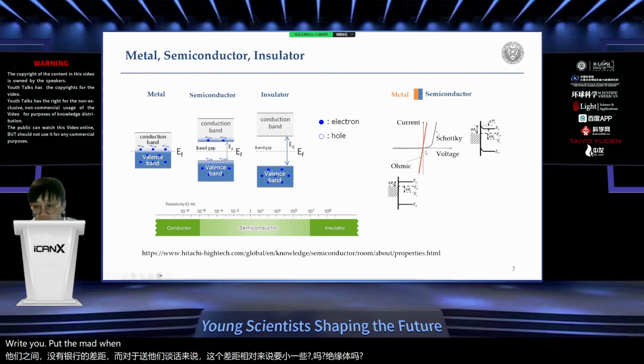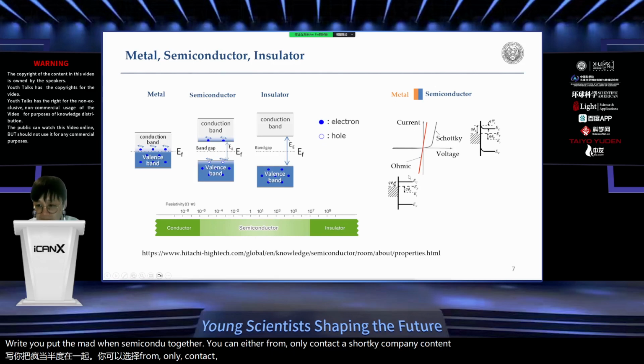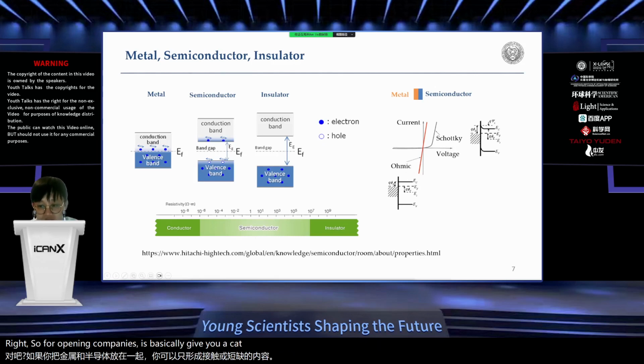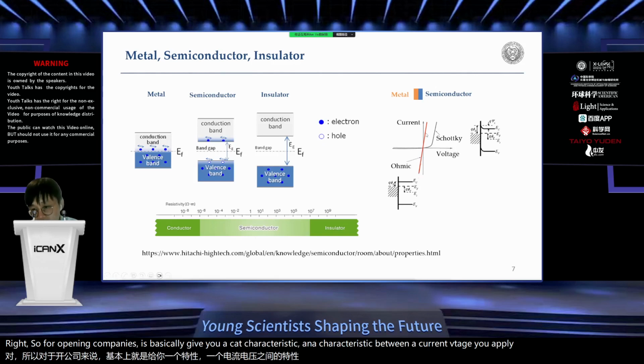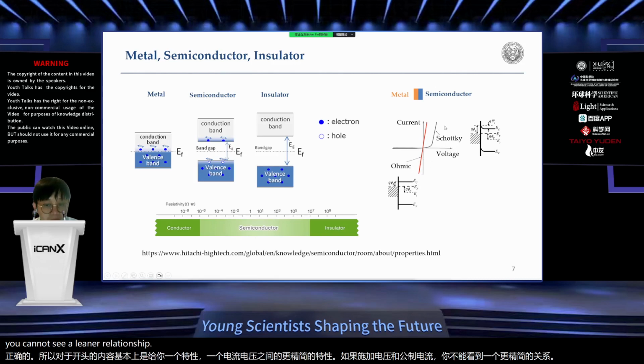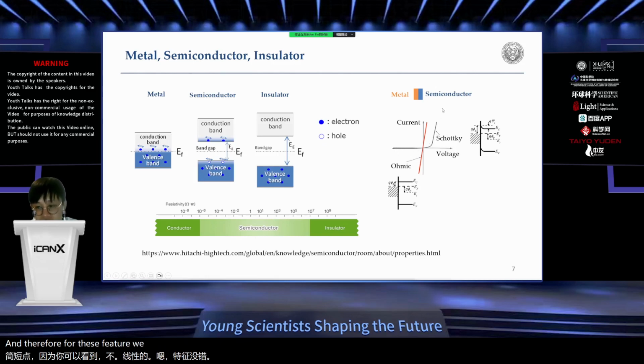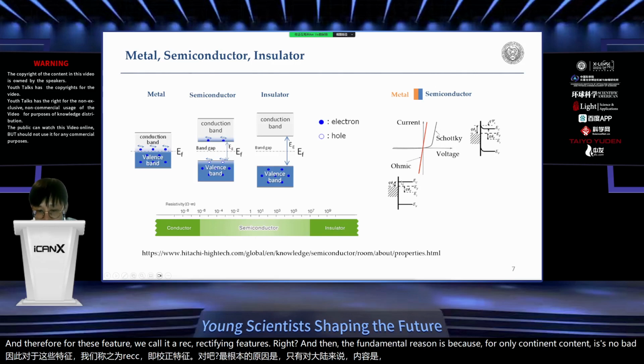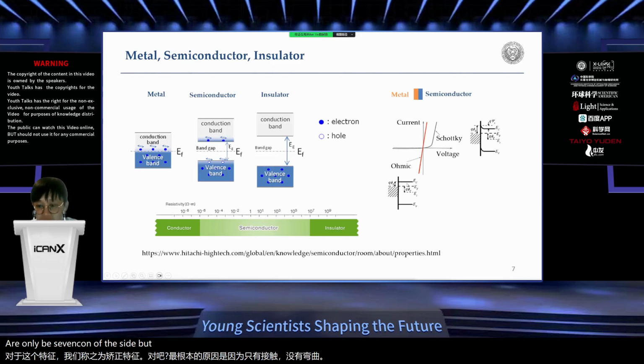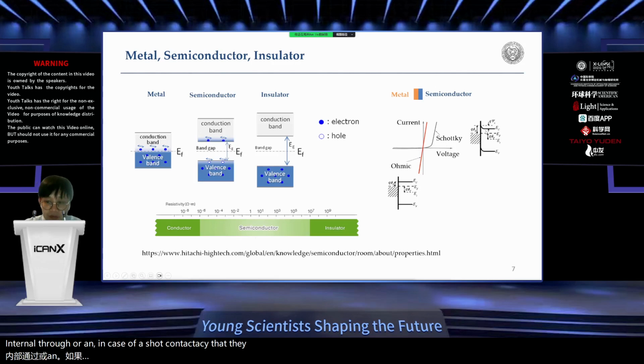And if you put the metal and semiconductor together, you can either form ohmic contact or Schottky contact, right? So the ohmic contact basically gives you a linear characteristic between current and voltage. If you apply voltage and measure currents, you're going to see a linear relationship. But for Schottky contact, you can see nonlinear features, right? And this feature we call rectifying features, right? And the fundamental reason is that for ohmic contact, there's no bending on the semiconductor side, or you have a really narrow depletion layer where the electrons can tunnel through. In the case of a Schottky contact, you can see that there will be a bending, and then there'll be an energy barrier for electrons, for example, to go from metal to the semiconductor side or from the semiconductor side to the metal side.